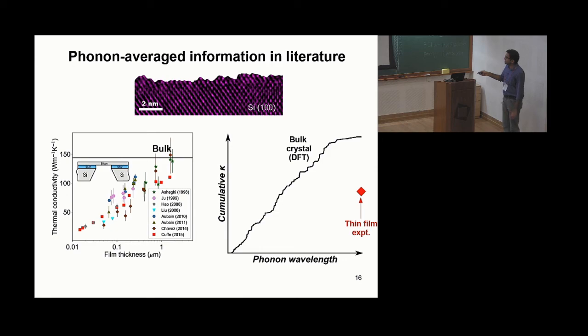And then as the thickness is reduced, the thermal conductivity starts dropping down. But this doesn't really give you mode-resolved information, right? All of these are just thermal conductivity measurements, so you don't know which phonon is really getting scattered at the boundary and which phonons are not.